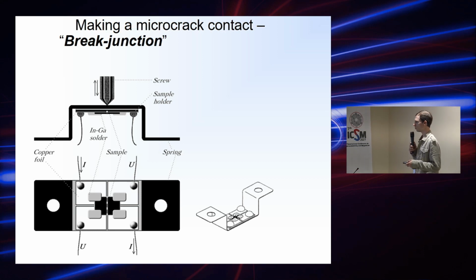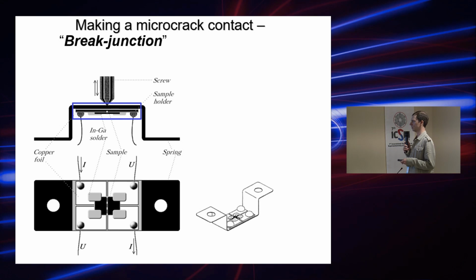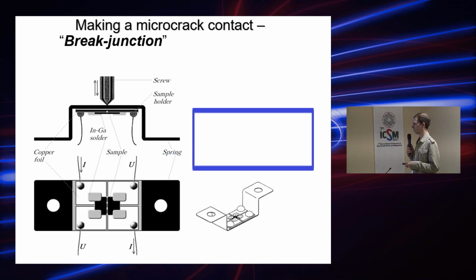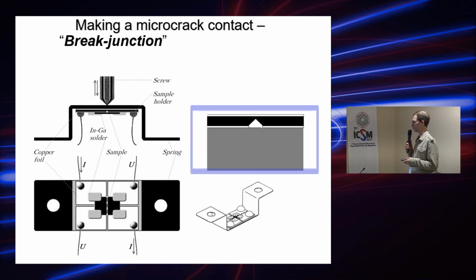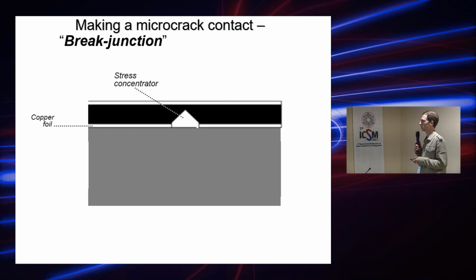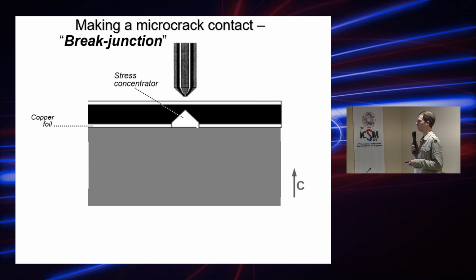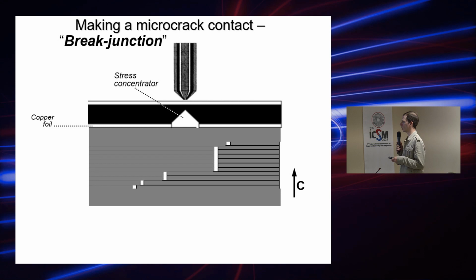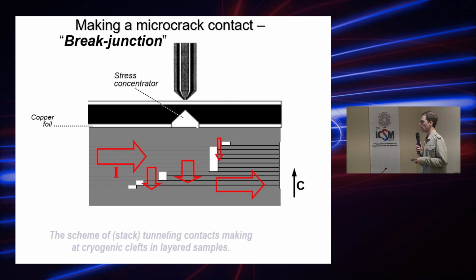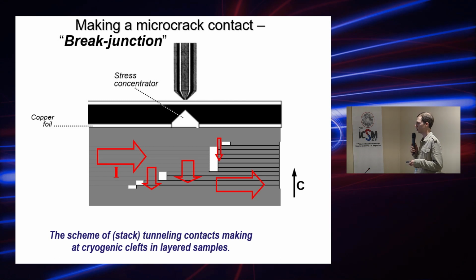Then if we try to bend this spring, you will see what typically happens for layered materials and layered superconductors as well. So it's a copper foil, and somehow we produce this stress, and we get splitting of the sample because we put it directly in the AB plane, and the C direction you see is perpendicular, so it splits typically into layer and terrace structures, producing some net of constrictions.